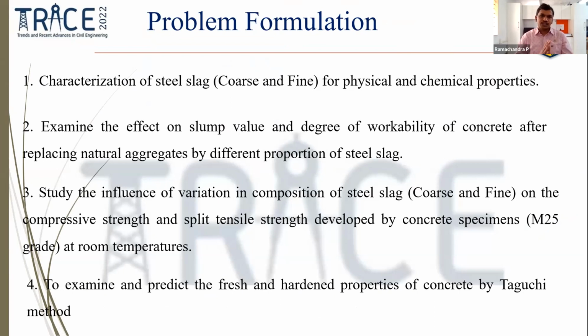Here I have used both coarse aggregate and fine aggregate of steel slag in my research work. Here is the characterization of steel slag for physical and chemical properties, and to examine the slump value and degree of workability of concrete, replacing natural aggregates with different proportions of steel slag, and the influence of the variation of coarse and fine on compressive strength and split tensile strength at room temperature. What I have introduced especially is predicting the hardened properties of concrete by the Taguchi method. Basically, we can predict the exact compressive strength and split tensile strength by this approach called the Taguchi method.